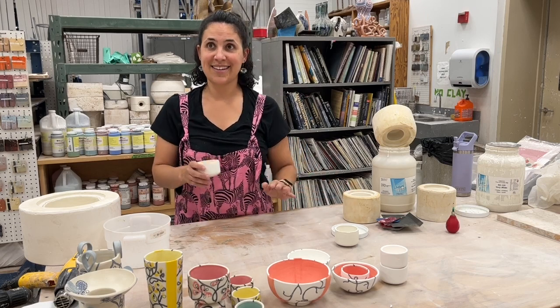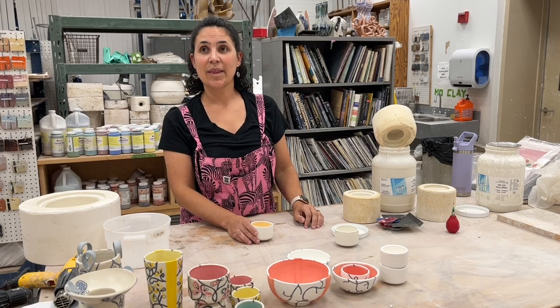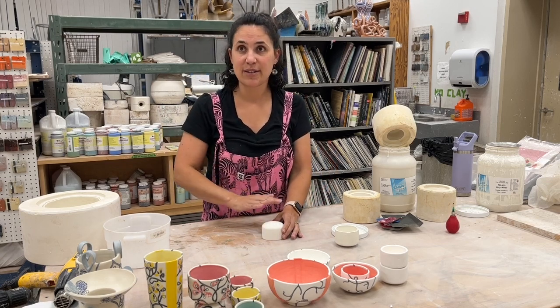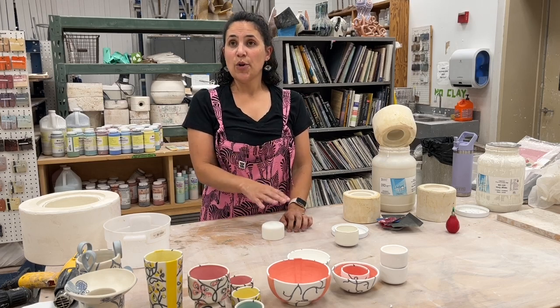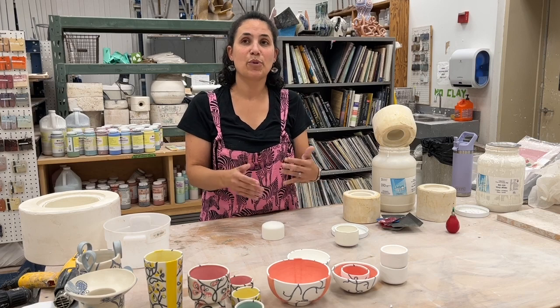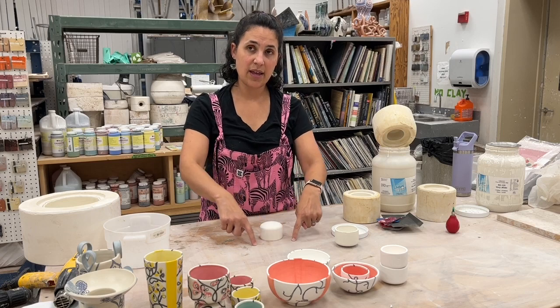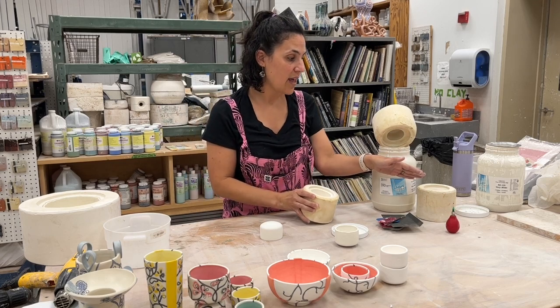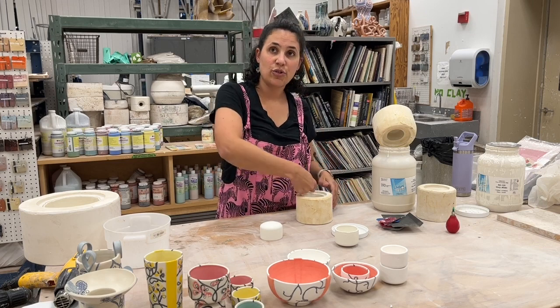To give a really basic question — starting with a piece of PVC pipe, you're coating it in plaster? Yes. So I take the PVC pipe — it usually has some markings on it, so I'll sand the surface a little bit and make it smooth. I use Murphy's Oil Soap and coat the surface to give it a little bit of a slippery release surface. Then I'll cut a circle of clay so I have this little inset area, a little lip for overflow.